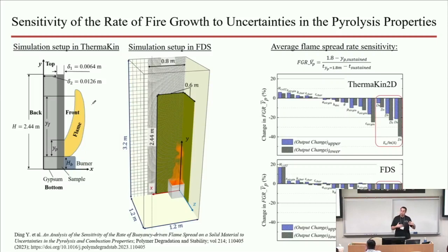There is a fairly large set of standard material science tools that measure this property. Yet the uncertainties that come out of these tools, on the order of 10-15%, are large enough to put us significantly off track. So this is another material property which we really need to understand better.